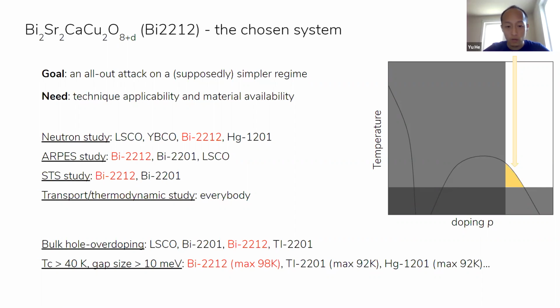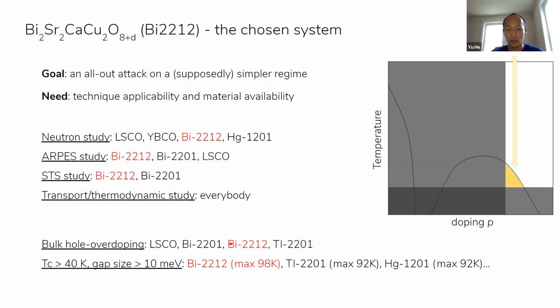That's a very good question, Timia. So for thallium 2201, that initial quantum oscillation work mapped out a large Fermi surface. I think the observation was pretty clear, where the oscillation frequency is high. But the argument can always be that so long as you have a high enough field and a low enough temperature, you can always get quantum oscillation. So for other cuprate systems, in particular bismuth 2201, the single-layer cuprate compound, and bismuth 2212, the bilayer cuprate compound, a large coherent Fermi surface has been observed all the way up to the point where superconductivity disappeared. And the volume actually is comparable to those measured in the thallium system. I hope that answers your question.